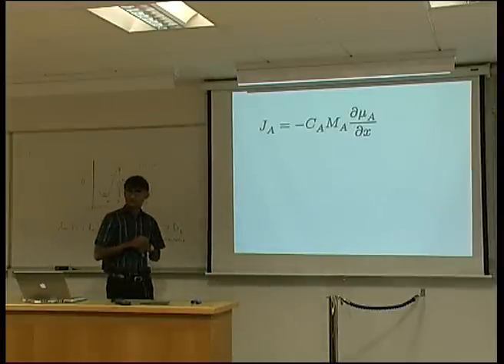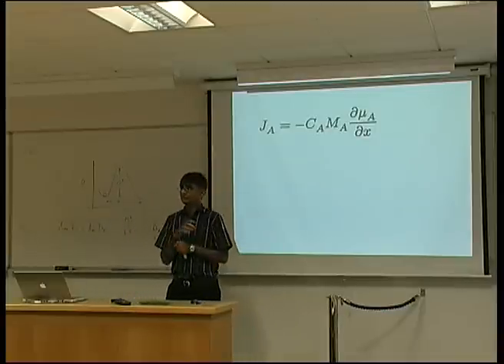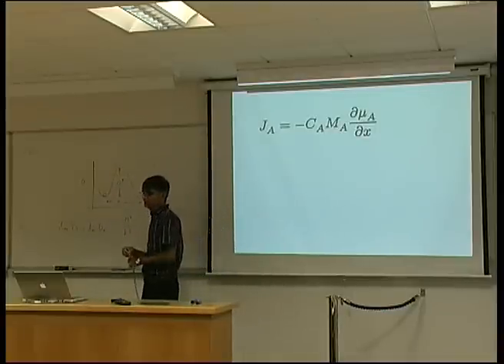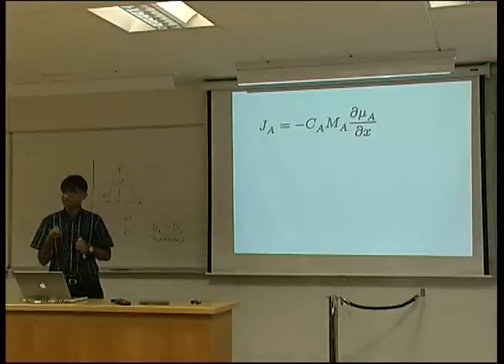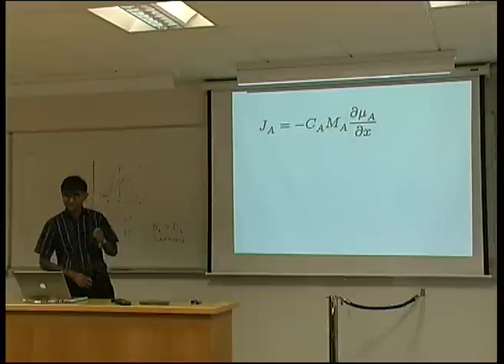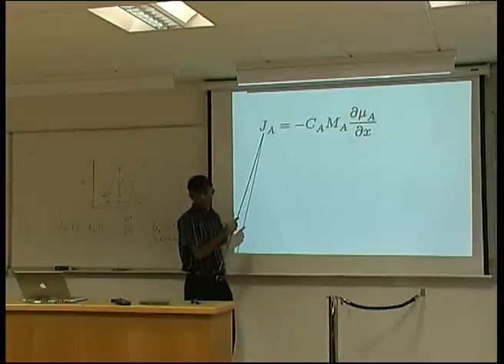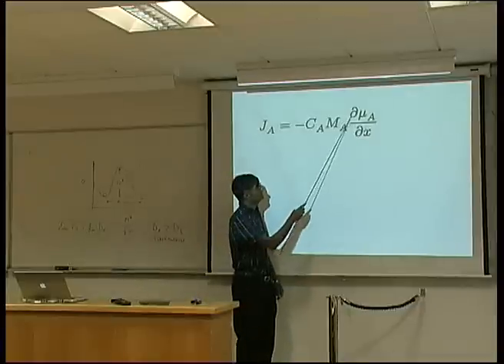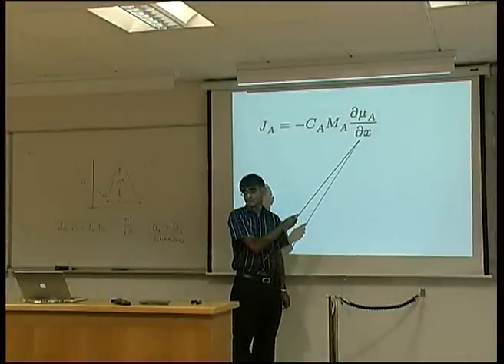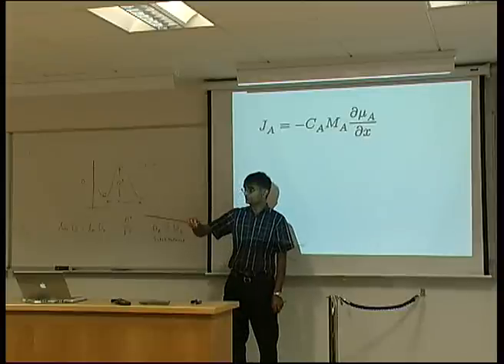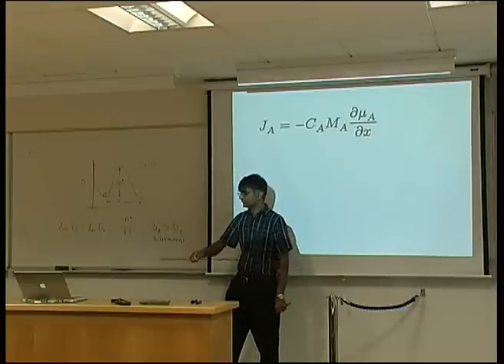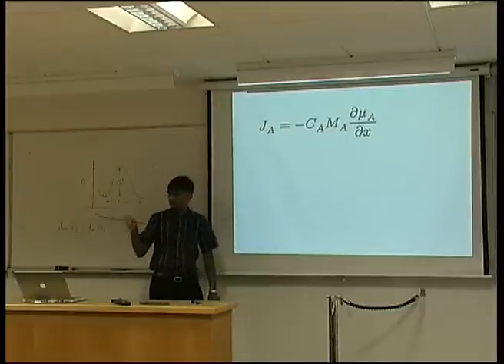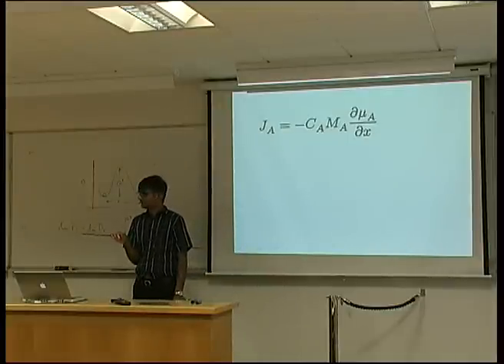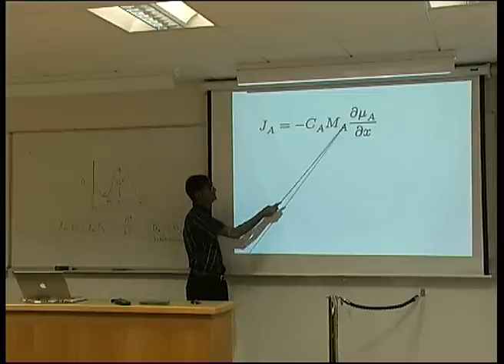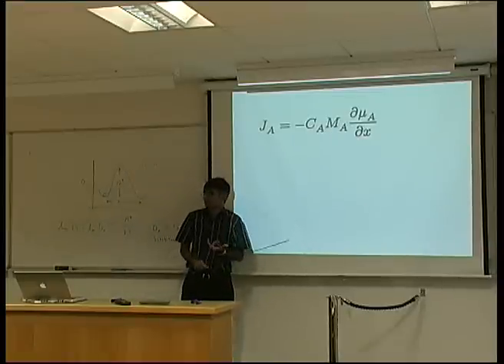Finally, just to leave you with something to think about for the next lecture, strictly speaking, diffusion is driven by free energy gradients, not by concentration gradients. So here we have the flux of A will be related to the chemical potential gradient of A. Remember, chemical potential is the mean free energy of an A atom in a solution of a particular composition. And everything will happen to reduce that gradient of free energy. And we no longer have the diffusion coefficient here, but we have another term which we call the mobility.